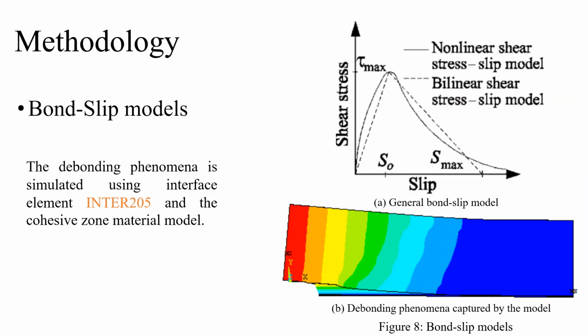In order to simulate the separation of the CFRP sheet from the concrete substrate, which is the typical failure mode of externally bonded reinforcement systems, Inter 205 elements were used with the cohesive zone material model. In this model, the shear stress is a function of the slip between the FRP material and concrete. The typical bond-slip model starts with an increasing segment up to the ultimate shear stress and its corresponding slip, as can be seen from Figure 8a. After that, a softening response takes place until the maximum slip occurs. The Nakaba et al. bond-slip model was assigned in this problem.